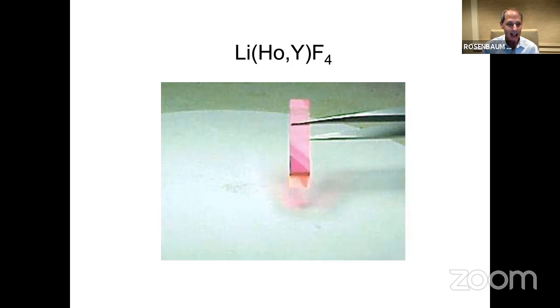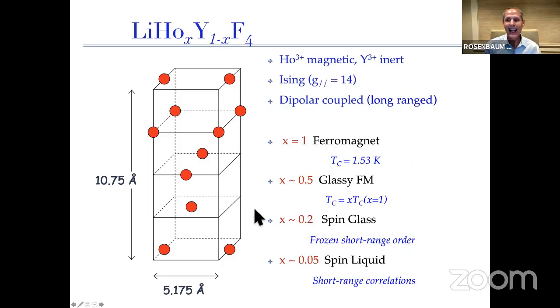Yttrium is non-magnetic, and that then allows you to tune the energetics of the system, and in fact, the ground state. So this is a less pretty picture of lithium, holmium, yttrium tetrafluoride, but it shows you the crystal structure. The crystal structure is a body-centered tetragonal system. The red dots, I've just shown you the magnetic sites. That's where the holmium, or substitutionally the yttrium, fits.